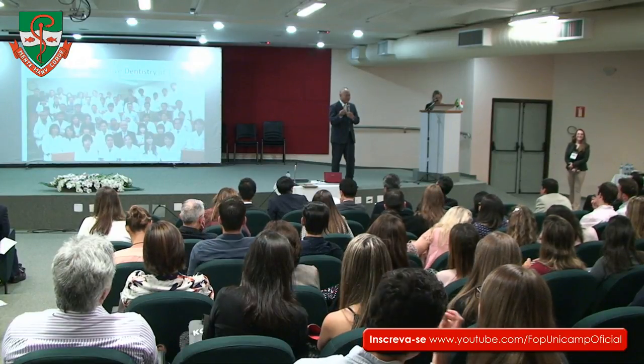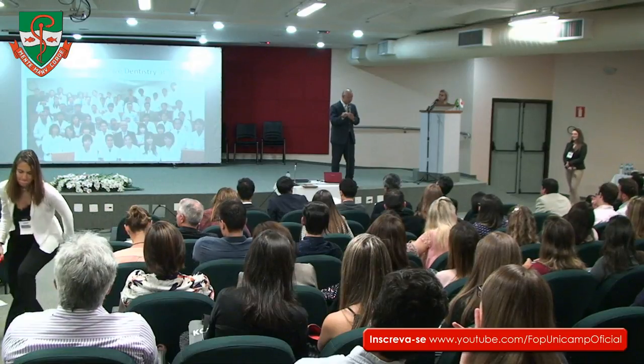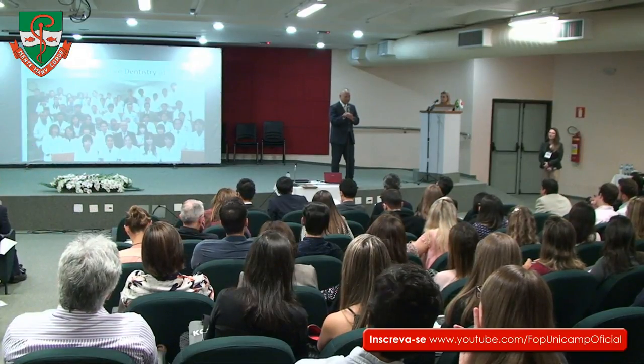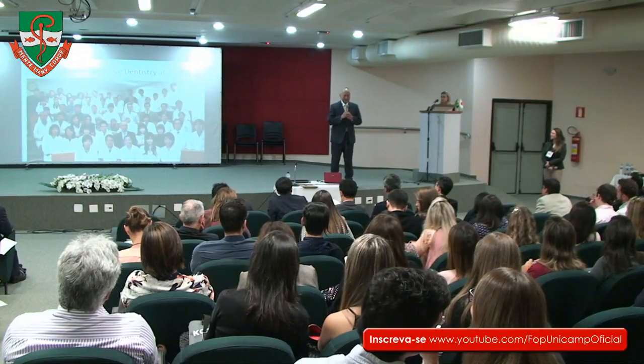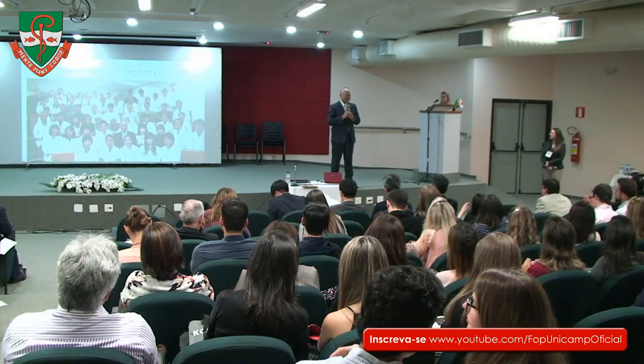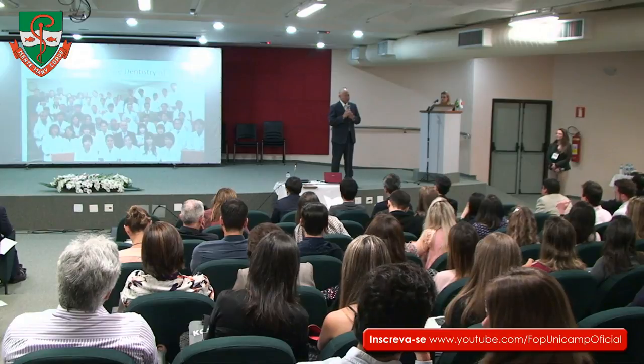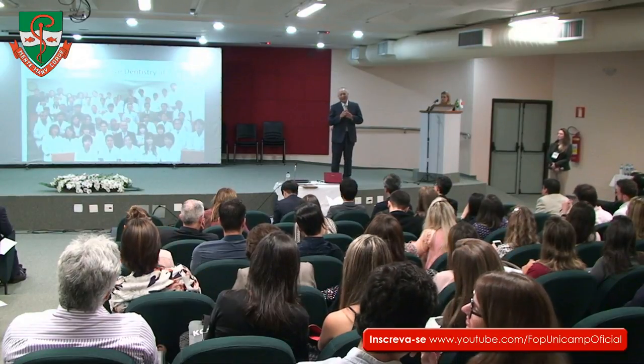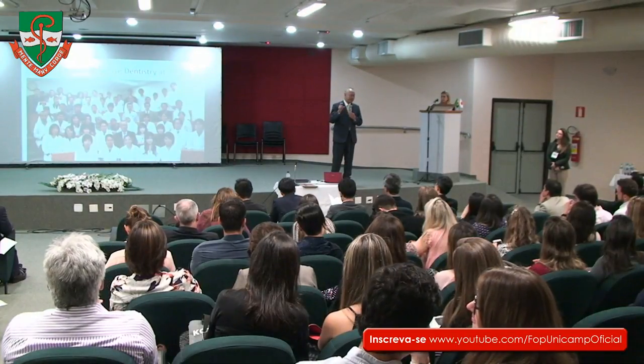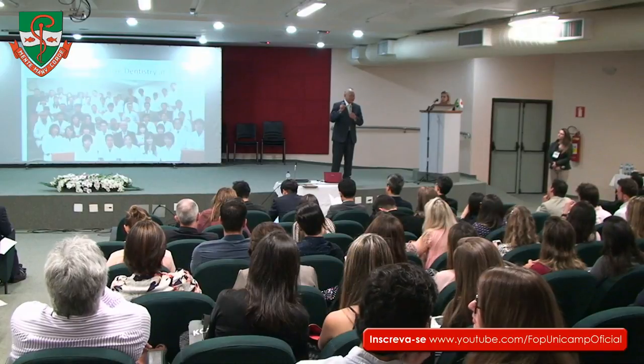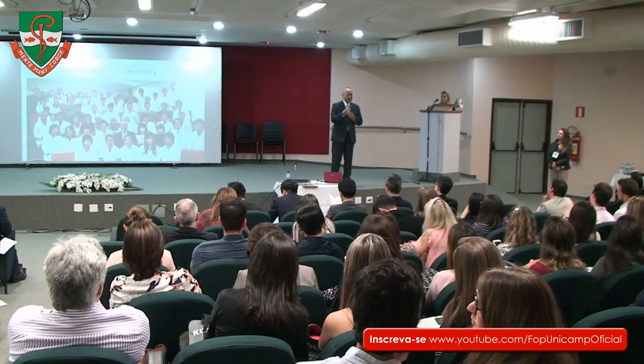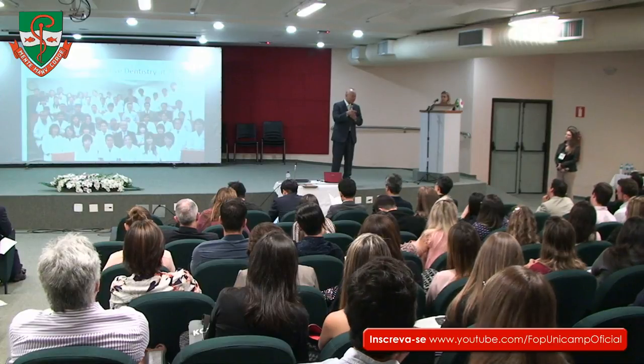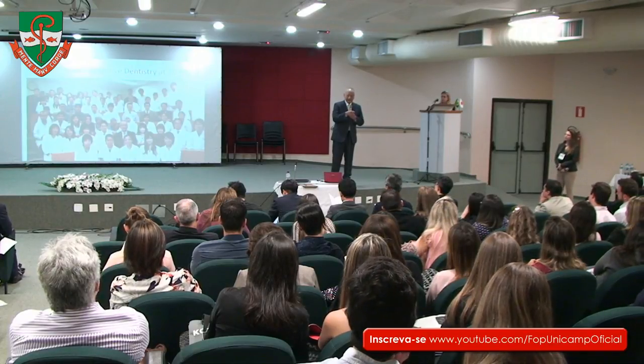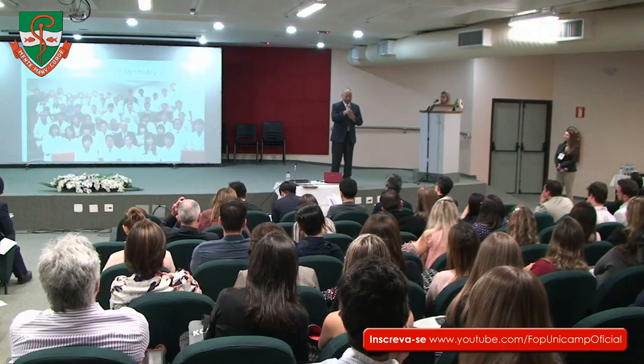Enamel, dentin, and many kinds of restorative materials, like ceramic and metal and so on, with just the same bottle of the adhesive. But the bonding to the ceramic material is not so easy. One of the so-called universal bonds is said to have the silane already activated with acidic resin monomers in the bottle. And the other material, I recommend us to mix the silane coupling agent with the bonding resin material. So it is activated immediately after the mixing.